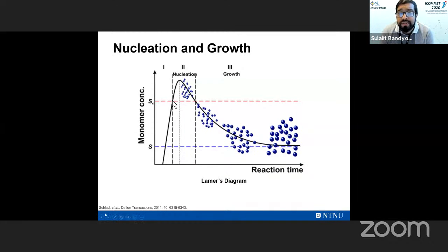Once the critical supersaturation for nucleation is reached, the first nuclei form. And as you can see, the nucleation window marked by region 2 is very narrow. The narrower you can keep it, the smaller the particle size and the more monodispersed particles you will get at the end. Once the nucleation has happened, nucleation drains the supersaturation. So you go down in supersaturation, and below Sc, there is no further nucleation possible, and growth continues for the later part of the process. So what this diagram conceptually does is separate nucleation and growth on an energy landscape and make it easy for us to understand how nanoparticles form.